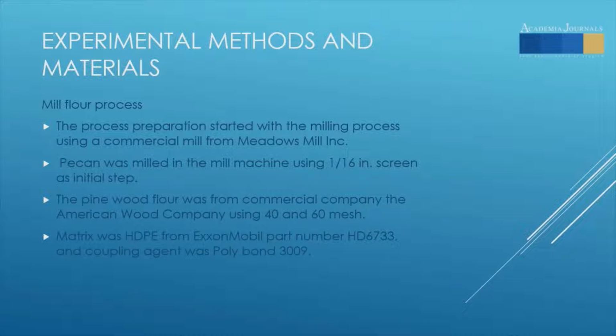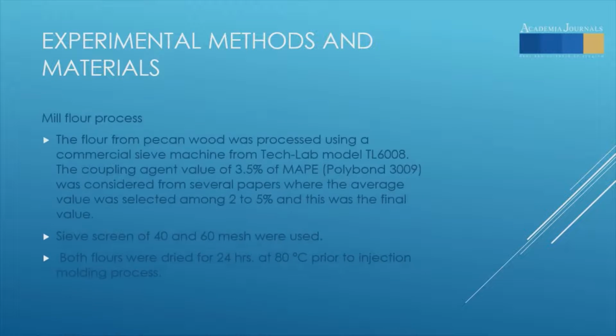In the mill flour process, we use 1/16 inch for screening, the first step. The pine wood flour was from American Wood Company using 40 and 60 mesh. We use HDPE from ExxonMobil Company. The mill flour was finalized by sieving the pecan wood flour using 40 and 60 mesh. Both flours were dried at 80 degrees centigrade for 24 hours.